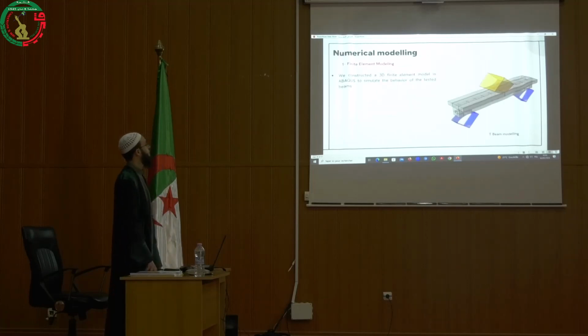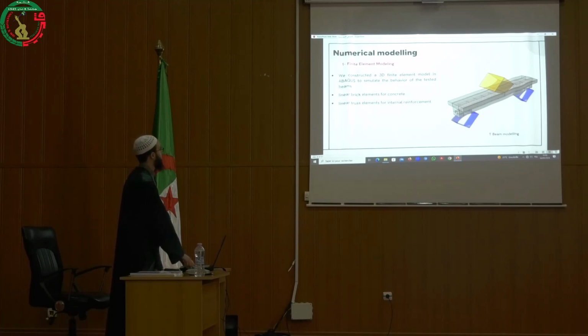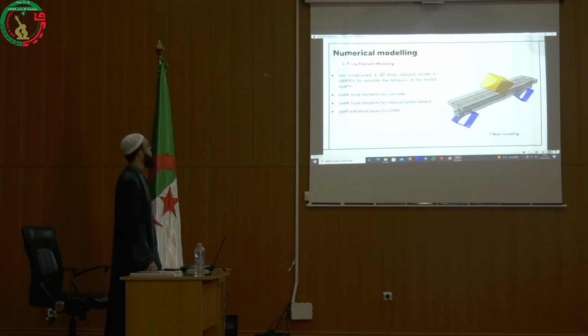We constructed a 3D finite element model in Abaqus to simulate the behavior of the tested beam. The concrete material was represented by linear brick elements, and steel by linear truss elements. The CFRP laminate was modeled by shell with 3 layers with different directions.